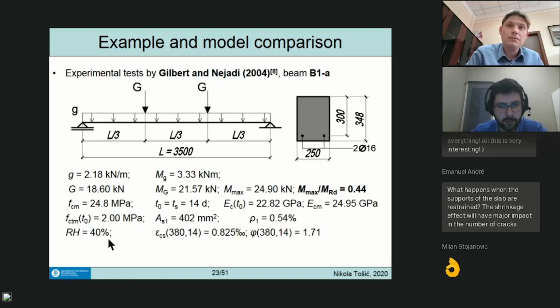Humidity was generally 40%, and these were the final measured shrinkage and creep values. Final, I mean at 380 days. The shrinkage strain, and this is when talking about the uncertainties of creep and shrinkage.